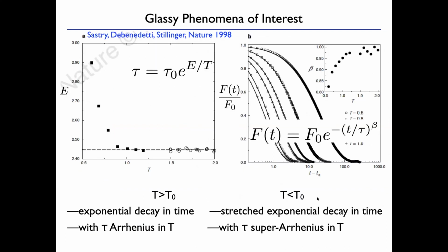It's interesting that if you look at how some stress relaxes as a function of time. So apply some stress, watch it relax as the system equilibrates, okay? You can fit it to a stretched exponential function, okay? Where the stretching exponent is 1. In other words, it's just purely exponential at high temperatures, but once you get below some characteristic temperature, which is the same temperature, by the way, that we saw where the energy barrier started going up, T0, this onset temperature, the stretching exponent starts to decrease, okay? So the relaxation becomes less and less exponential, more stretched as you lower the temperature below that onset temperature.